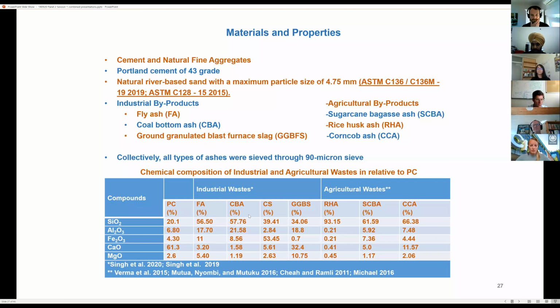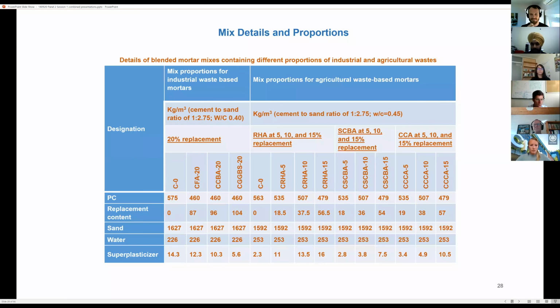If you look at the chemical composition of these industrial and agricultural wastes, they all contain chemical compounds related to those of PC. So that's why they are easily replaceable, in certain amounts, for the generation of the specimens or the mixes. This table shows the replacement levels and the various mixes we have made. For industrial byproducts, we have chosen a constant replacement level of 20% and made the specimens. Likewise, for agricultural byproduct based blended mortars, 5%, 10% and 15% replacement were made, and certain mixes were cast.